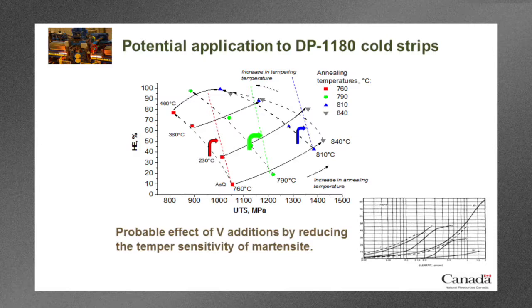There is an assumption here that needs to be proved experimentally, and it hasn't been: that if we reduce the temper sensitivity of the martensite, for example by using vanadium, we still keep the same gain in hole expansion that we obtained due to tempering. And that needs to be proved. We don't actually know that for sure. Experiments need to be done.